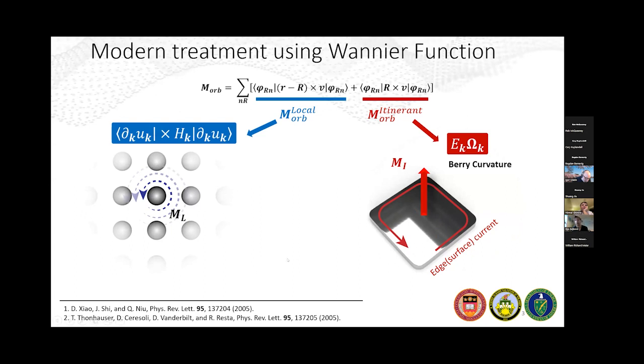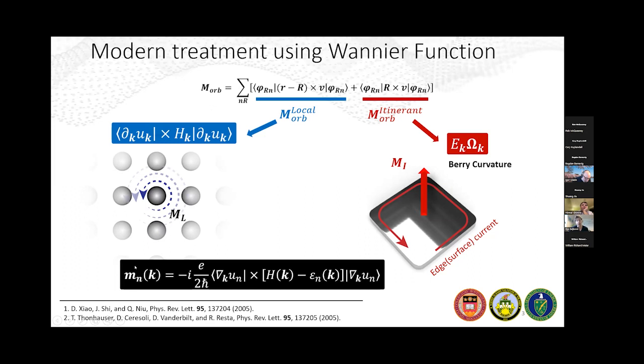So here are some of the relevant references where this was put forth. But the basic idea is that the contribution stems directly from the Berry curvature of the electronic bands. So different parts of the electronic bands will carry different orbital magnetic moments. And as such, orbital magnetic moments associated with different electronic states are going to be momentum dependent. So you will see a lot of this m_n(k). This is the orbital magnetic moment associated with different bands and with different momentum of the electronic state, which can, in principle, be calculated.